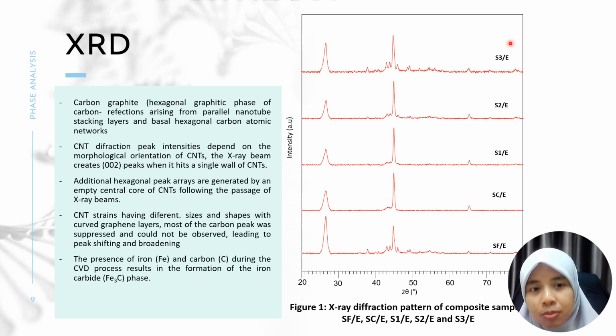So we could see that actually carbon graphite or hexagonal graphitic phase of carbon reflections arising from parallel nanotube stacking layers and basal hexagonal carbon atomic networks. And CNT diffraction peak intensity depend on the morphological orientation of CNTs. So the X-ray beam creates 002 peaks when it hits a single wall of CNT. So actually this is the 002 peak, which is dominant for carbon graphite peak.